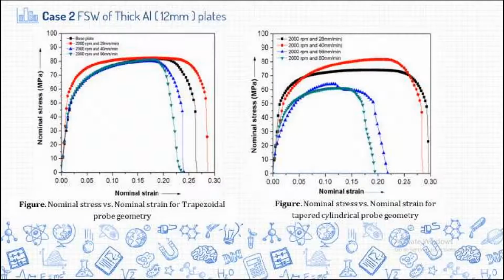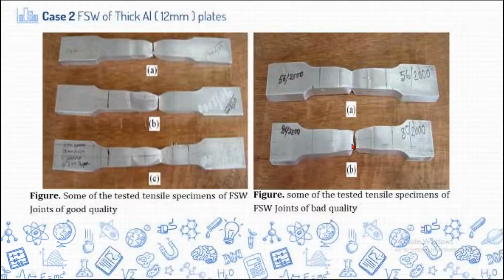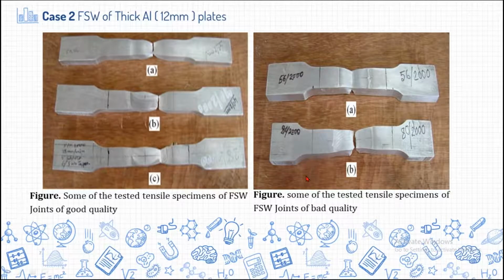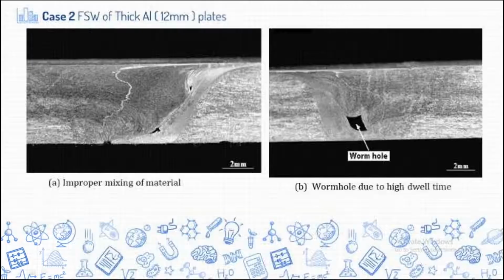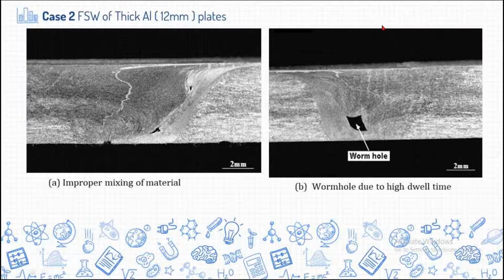So we want to see what happened, what is the reason for this failure at the center. We did some microstructural examination using a microscope. Here we observed some defects in the center of the welding. We expected this kind of through hole is due to improper mixing of material on both the sides, and there is a wormhole